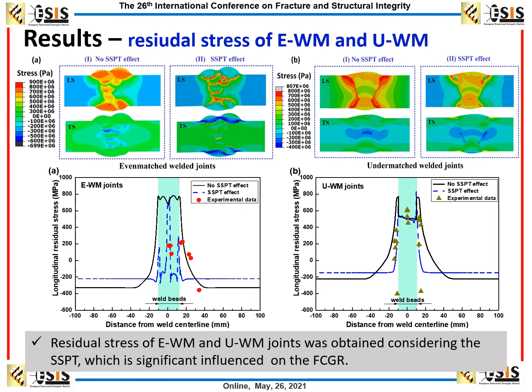However, for the undermatched weldment, the residual stress distribution has great agreement for both considering the SSPT effect or no SSPT effect. So the residual stress of the even matched and undermatched weldment is better considering the SSPT effect, which has a significant influence on the even matched FCGR.